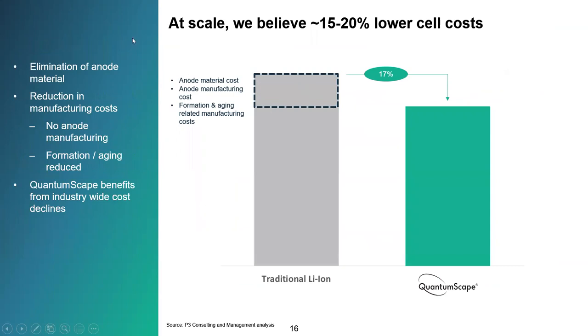I wanted to just touch on cost quickly and not get into too many details, but Quantumscape's internal analysis shows that by eliminating the host materials for the anode and the manufacturing, there's a whole manufacturing line that's required to make a traditional anode. By getting rid of that, because it's an in situ generated anode in our case, we can reduce the overall cell cost by between 15 and 20%. So the cathode is basically the same. Instead of the conventional electrolyte, we have to make our solid electrolyte, which has some differences, but all in, it's a little bit of a cheaper system with, of course, the other advantages.